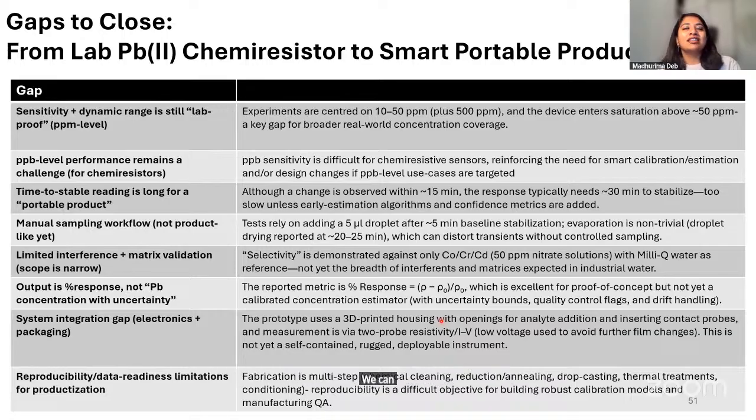We only did 10 to 50 ppm. Though we tried other concentrations also, it did not go to the ppb level. For industrial use that may be okay, but for some home water supplies we would want the level to be below ppb.